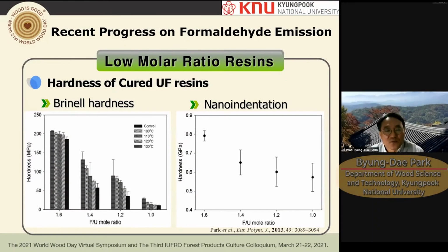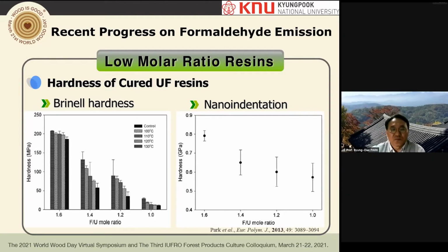And what I did is we prepared films of the UF resin and then cured them at different temperatures, depending on different molar ratio resins. As expected, higher molar ratio gives much higher hardness compared to the low ones.